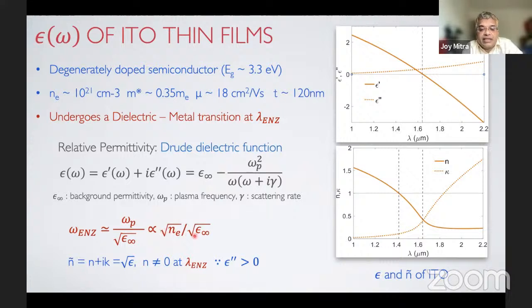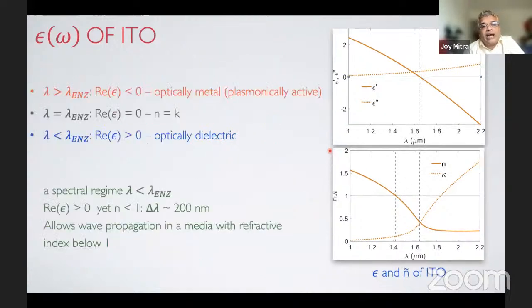So this is what really fascinated me and people working around me, that you have such a system where if you change the number density, you can tune the ENZ wavelength. But as with realizing many of these exotic properties, the bulk of the research actually goes into preparing the right material. How far can you actually control the material so that it is reproducible, stable, and robust in terms of the results? So the first part of our exercise was essentially to look at the material aspects of indium tin oxide.